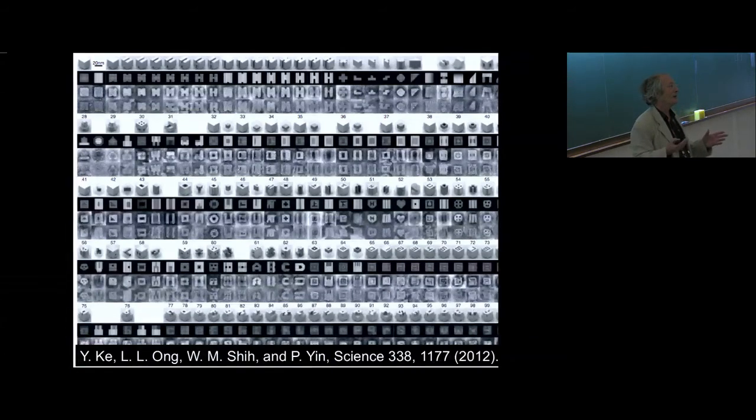Cube, not very exciting, but every particle in the cube has to be in the right place. And then you see that you can have a cube as a whole, you can have numbers, you can have letters. What you see here typically is the design structure. Then you will see what you get from a single electron micrograph, and this is what you get if you average many electron micrographs. So actually, all these different target structures have been reproduced and actually have been observed to form in these experiments.